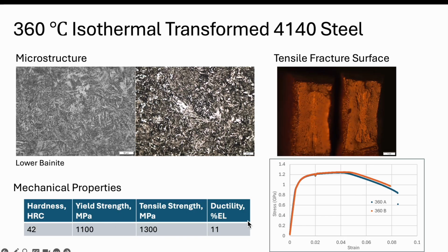So when we look at these samples, the fracture surfaces of the tensile samples, we see more deformation. You might actually see that the shape has changed. These were the same exact shape as the previous. That change in shape means there's more plasticity, more ductility, which you're seeing down here, and there's less flat surface, right? The flat part means more brittle, and so we're seeing less of that here. So we can also see that on this structure.